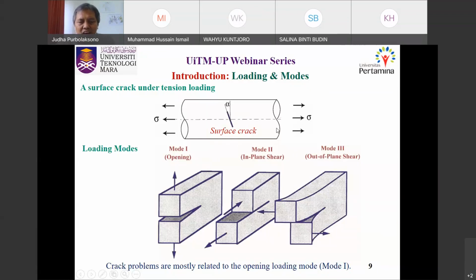Of course, if alpha equals 0 and it is subjected to tension, we do not have loading modes 2 and 3. And if alpha equals 0 and it is subjected to torsional loading, then we do not have a result for mode 1. Actually, we have, but it's close to 0. Anyway, in practical applications, the opening mode, the mode 1 stress intensity factor, is mostly used. That's why mode 1 is more likely to happen.